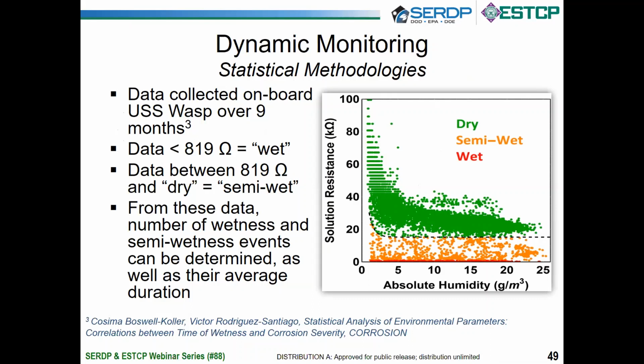So we can apply statistical methodologies that were developed by Cosima Boswell-Koller, as well as Dr. Victor Rodriguez-Santiago here at Naval, to get a better idea about how many dry versus semi-wet versus wet data points a system can be exposed to. With this knowledge, we can also assess the exact corrosion. We can actually fairly accurately predict corrosion mass loss amounts for aluminum and steel samples, and we'll get into that a little bit later as well.